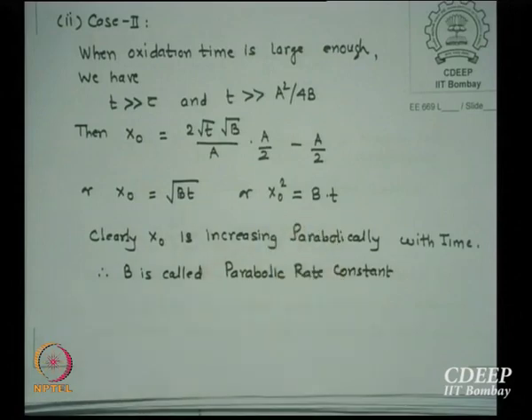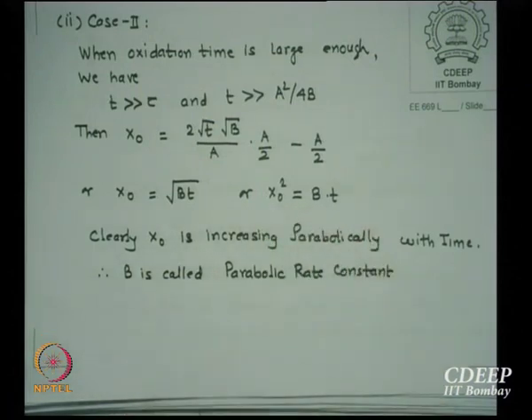So x0 growth is now under root of Bt, which means it reduces the oxidation rate, and therefore the oxide thickness growth slows as time is larger and larger. So initially linear and then parabolic growth starts in the case of oxidation. Since B gives the constant of parabolicity, we call B the parabolic rate constant. B is called the parabolic rate constant.